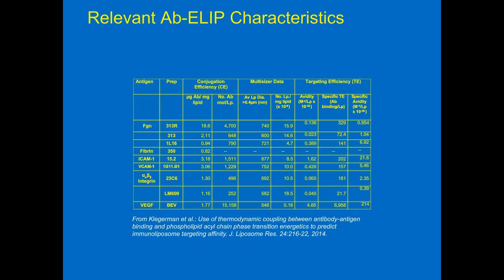It varies, but like I say, for porcine arteries that may or may not be atherosclerotic, you'd get let's say a baseline of around 15 using that scale, or 10, 15, 20, and then your non-specific with your liposomes might be a little higher, maybe 30, and then your specific are up to maybe 60 to 80. I'm just giving you some numbers that we have seen.